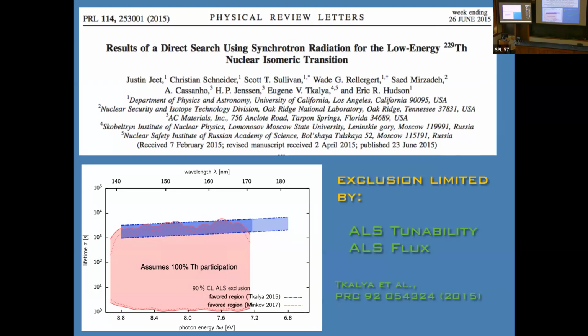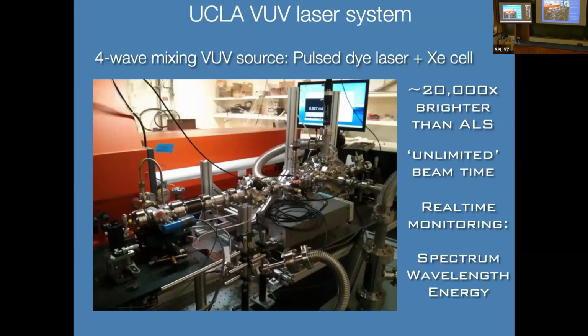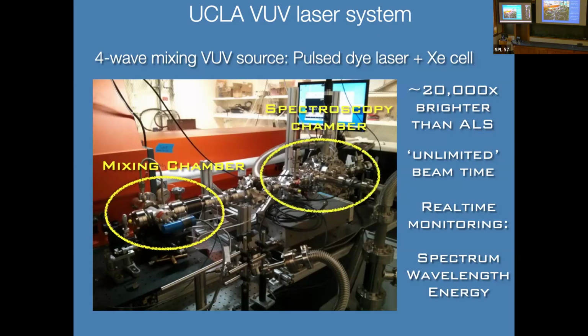So we went back to UCLA and we built a VUV laser system. It was about 20,000 times brighter than the ALS. It's much narrower, that's why, and so it takes much longer to scan over this region. There's a bunch of lasers here that get combined in a xenon mixing cell where we do some 4-wave mixing. And then here you can see that same chamber we had at the synchrotron.